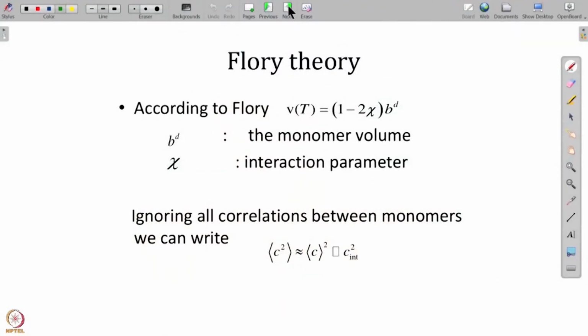So now Flory introduced a famous parameter again, called the Flory parameter, that is exactly that quantity 1 minus 2 chi, and he derived an expression for chi later which works out exactly according to this. So when chi is greater than half, then this is negative and is attraction, but when chi is small, then it is repulsion.